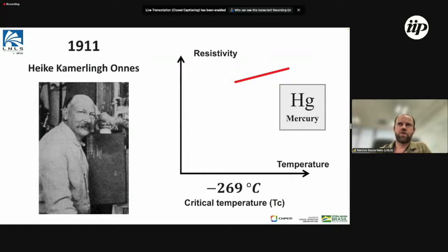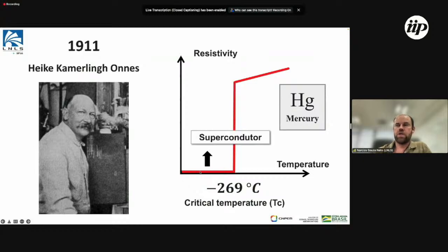More than 100 years ago, this guy here, Onnes, made the discovery after he liquefied helium, and then he put mercury and was measuring the resistivity of mercury at very low temperatures. And it was like that. But then when he went below a certain temperature, about 4 Kelvin or so, he actually saw a very quick drop of resistivity, and the resistivity below that temperature was zero. And that was what he called the superconducting state.